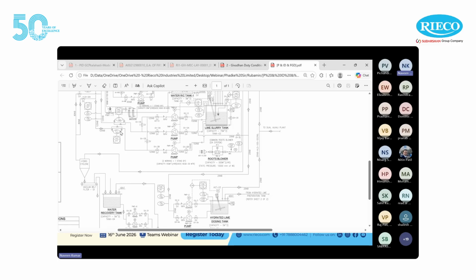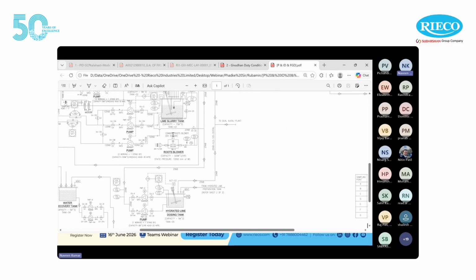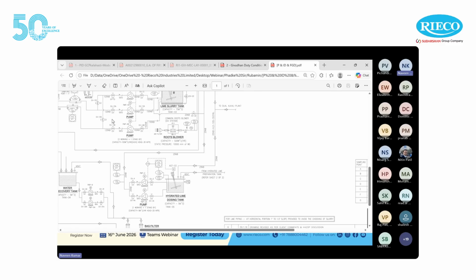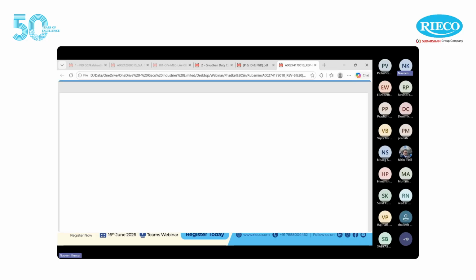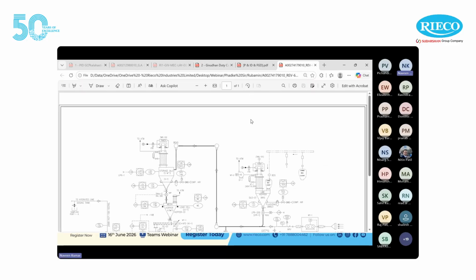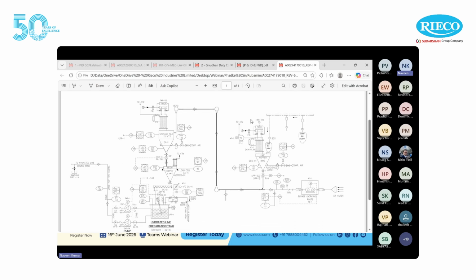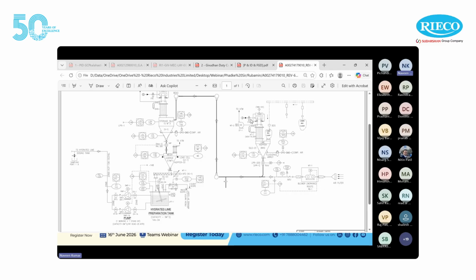There is a dosing system for dosing lime slurry in the recirculation tank of the lime absorber, and similarly a dosing system for dosing caustic in the recirculation tank of the packed bed scrubber. Then there is a material handling system for lime, which is essentially a loading system of pneumatic conveying to load the silo with the required quantity of hydrated lime. And then there is a weighing system where we weigh the exact quantity of hydrated lime and take it into a tank for preparation of lime slurry. This lime slurry is then transferred to the dosing tank for onward consumption in the lime absorber.